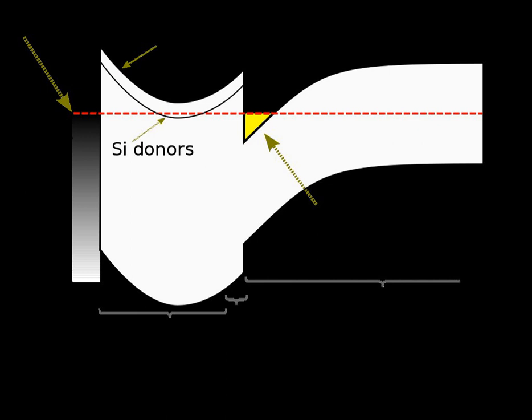Another way to use materials of different lattice constants is to place a buffer layer between them. This is done in the MHEMT or metamorphic HEMT, an advancement of the pHEMT. The buffer layer is made of AlInAs, with the indium concentration graded so that it can match the lattice constant of both the gallium arsenide substrate and the GaInAs channel. This brings the advantage that practically any indium concentration in the channel can be realized, so the devices can be optimized for different applications. Low indium concentration provides low noise, high indium concentration gives high gain.